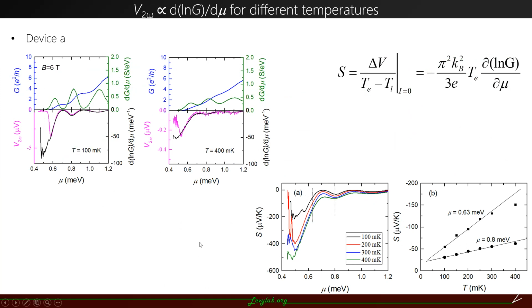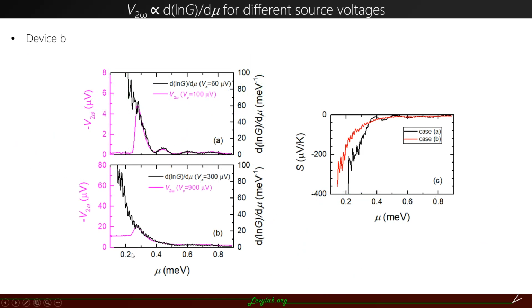We have tested the temperature dependence. At a fixed magnetic field, with repeated measurements at different temperatures from 100 millikelvin to 400 millikelvin, we see that the thermal voltage consistently compares well with d log G / d mu. And when we plot the Seebeck coefficient as a function of temperature, we find that indeed it shows a linear dependence on the temperature.